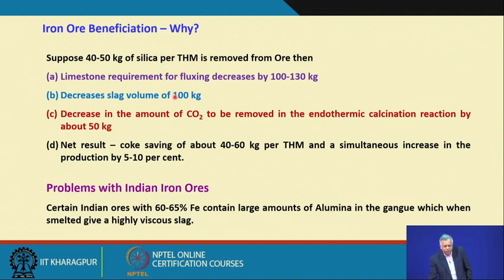And you do not have to understand all this; a bit of background in metallurgy is required to understand, but look at the final result. The net result is a coke saving of about 40 to 60 kg per ton of hot metal and a simultaneous increase in production by 5 to 10%. This is very, very important.